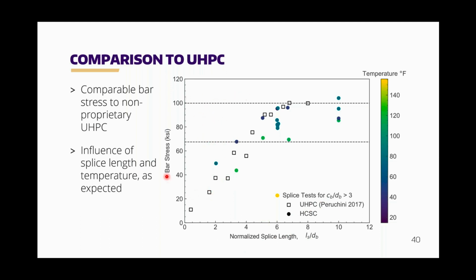And what you can see is, especially for the lower temperatures, which are shown by the darker blue color here, we're tracking very well with the non-proprietary UHPC. As temperature increases, as the dots become lighter green or yellow, you can see the yellow dot all the way down here, up at 145 degrees Fahrenheit, you get a change in the strength, and you see a slight reduction clearly indicated up here and also in this region. And that's what we'd expect, right? We know that the temperature is going to reduce the bond strength slightly. Overall, though, comparable to the non-proprietary UHPC.